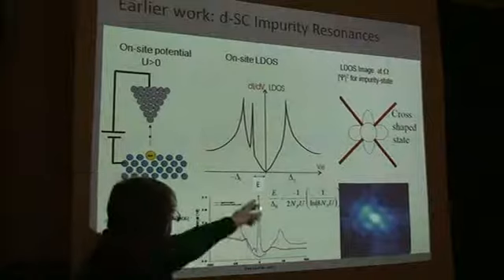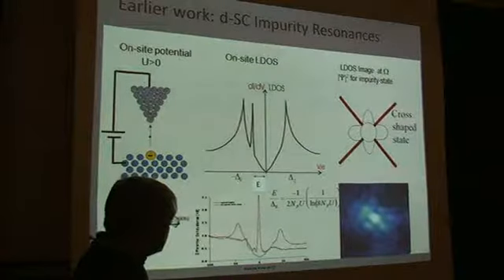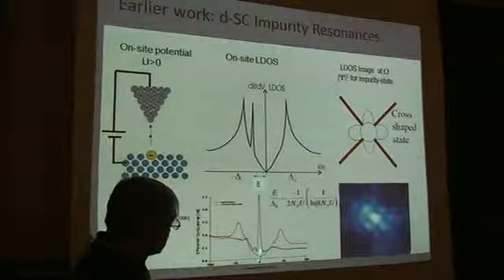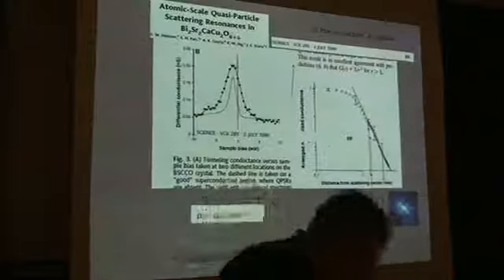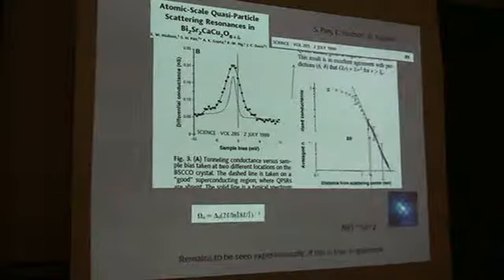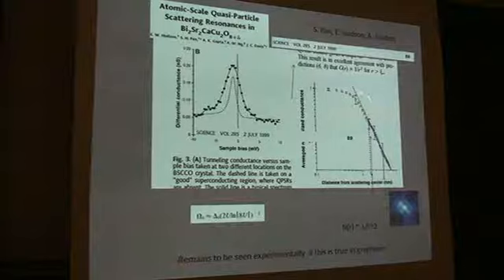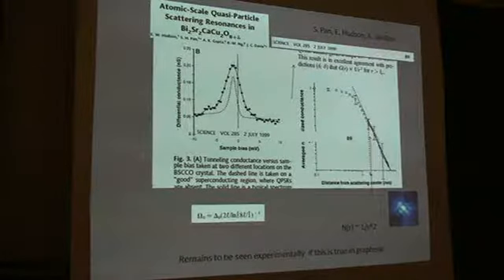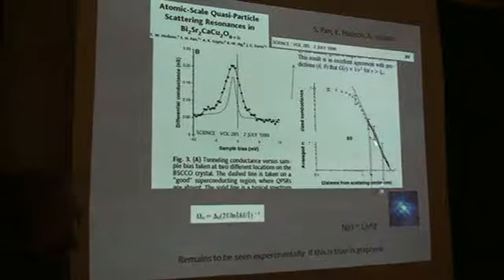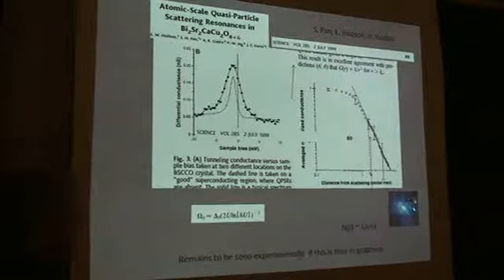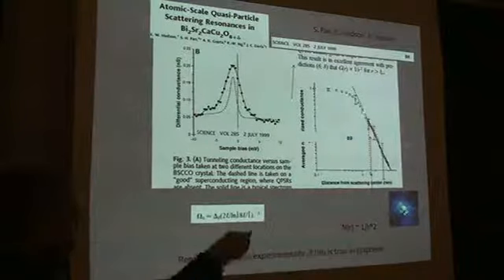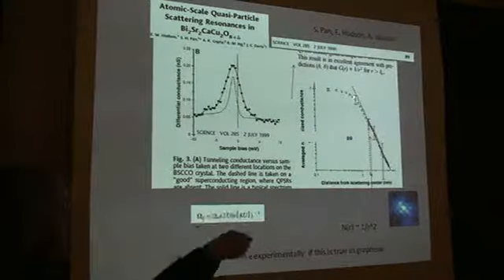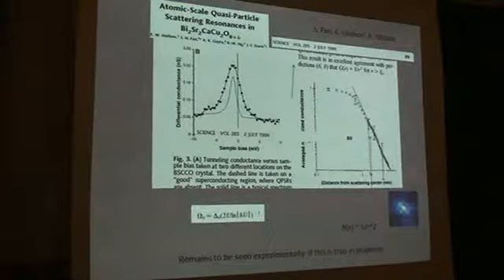And number two is the intensity of this. Yeah, this is a real space image. If I keep my bias at this value of about near zero, it's not exactly a mid-gap state, it's an intra-gap state, but not mid-gap. I'll see this intensity as I move around. Because it's a Dirac fermion, the tails will decay as a power law, and there is a very simple power law prediction of how it should decay, because it's a Dirac propagator in 2 dimensions. When Eric Hudson measured the tunneling conductance, he had to angle-integrate it to get enough signal to noise, but within the range of about 0.8 to about 2 or 3 nanometers, it does decay as 1 over R squared, as the theory predicts.